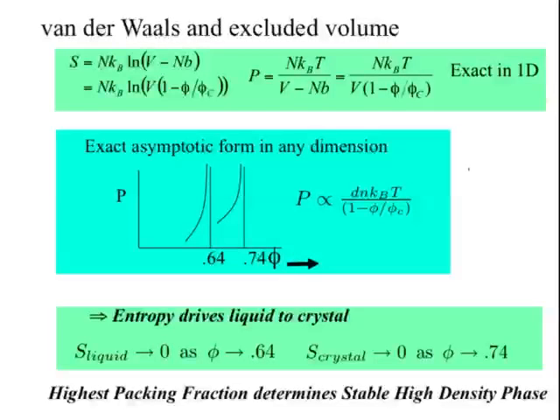And the entropy, in the region between 64 and 74%, is much higher for the crystalline phase than it is for the disordered phase. That sounds weird, right? Let's do it this way. You take this hall and you fill it completely randomly with spheres. You fill this place to 64%, right? And there's no motion, there's no entropy associated with that. There's no motion allowed, okay?